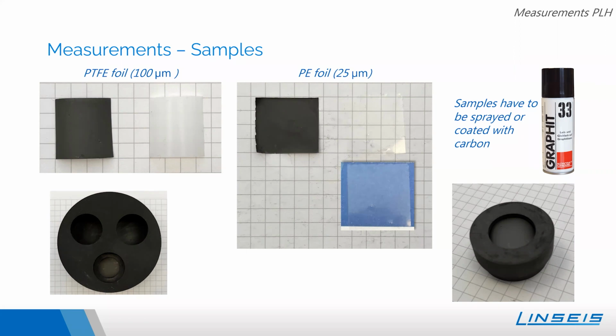But to enhance the signal, you have to coat your sample, and this is done with a standard carbon spray, which is displayed in the top right of this slide. This coating is needed to increase the absorption and the emission of the sample, so your signal gets higher and your results are better. In the lower left corner, you see one of our sample carousels with an equipped sample below. If you look at the bottom right, there is a close-up view of one of our samples within a sample holder. So there you see the sample is really plain in this sample holder.